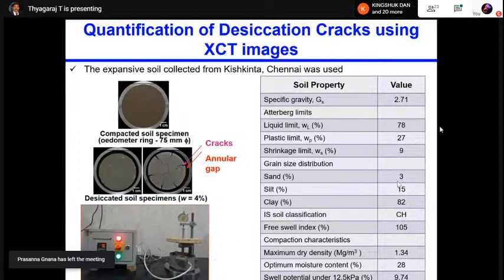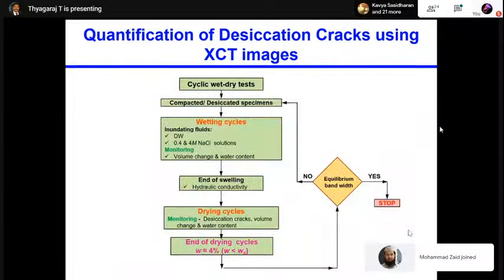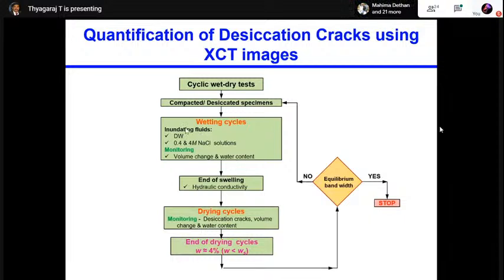We have used the soil from Chennai. It has a liquid limit of 78 and clay content of 82%, and the free swell index was 105. That's how we did the wetting and drying cycles. We have used three fluids: distilled water, 0.4 and 4 molar NaCl solution.